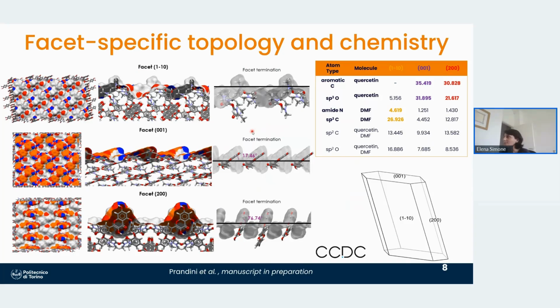And again, this is maybe a bit crowded, but what we've done is we grew a crystal using the crystal breeder, we indexed it to try and understand the facets that we could actually obtain experimentally and measure. And then using the attachment energy model, we created these maps. So those are the facets where we can see the rugosity of the facets, both from the top view and from the side. So we can see differences in the roughness based on, again, the position of the quercetin molecule and the DMF molecule compared to the plane of the facets.